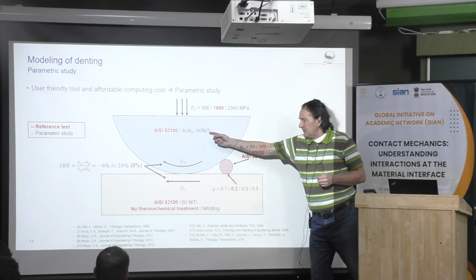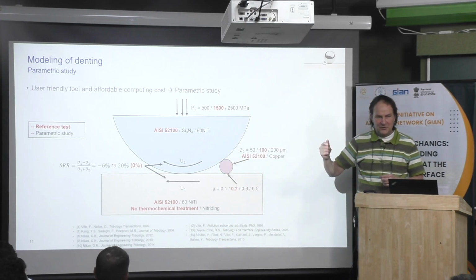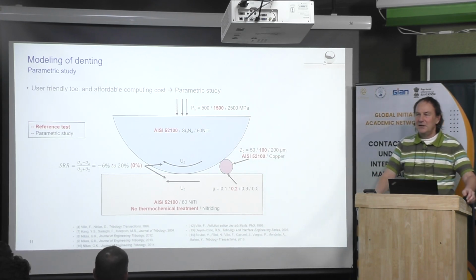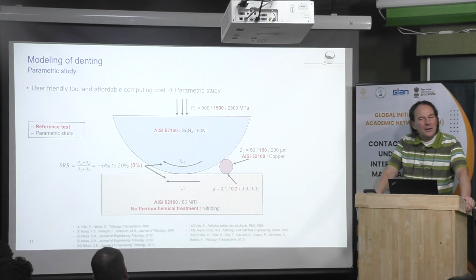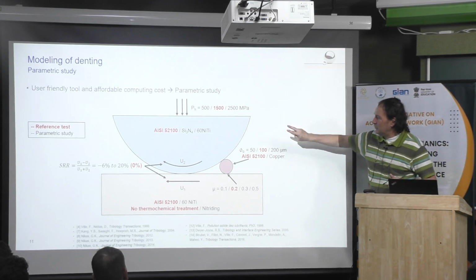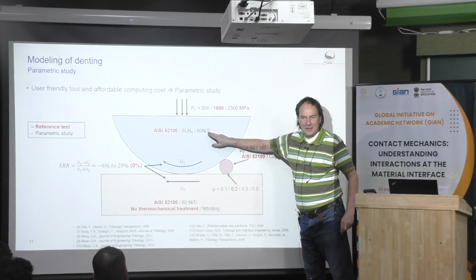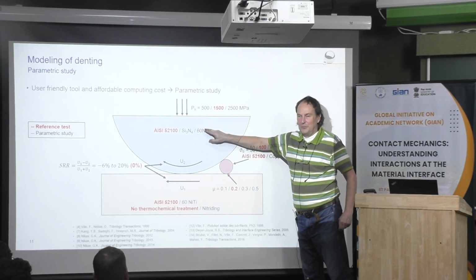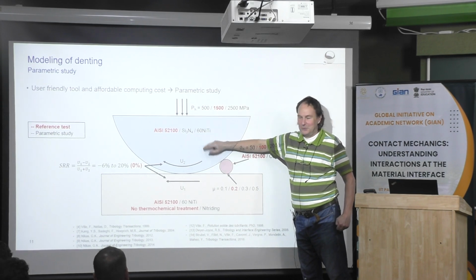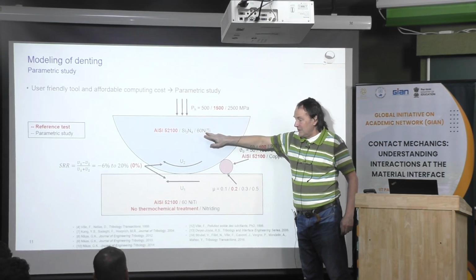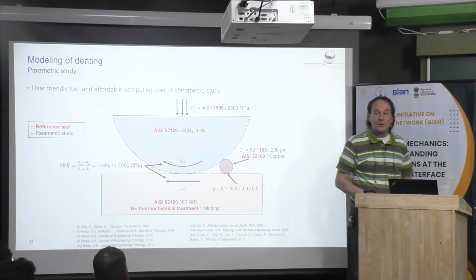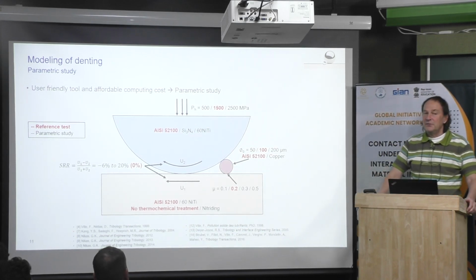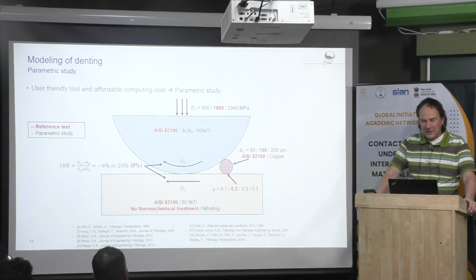And the last one is an interesting material. I don't know if you know this material, 60 NiTi. It's like a shape memory alloy, but this is not that. In fact, yes, but this is mostly when you invert the composition of nickel and titanium. 40 should be a memory alloy type. But this one is what we call a hyperelastic material. It has been developed by NASA very recently by Christopher DellaCorte. I don't know if you know him.